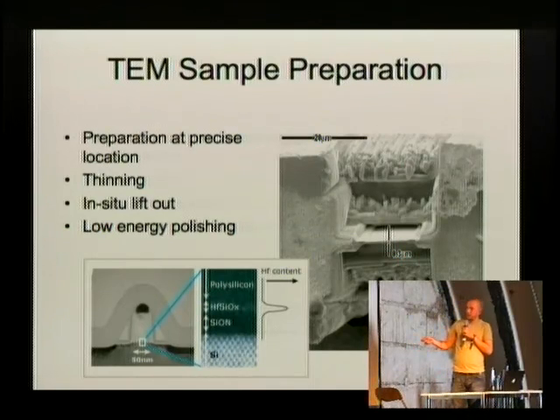Another thing we see here, I will talk about also on the next slide. In these microscopes, you can not only look at the image, you can also do, for example, some X-ray analysis, and that gives you very nice information about the material you're actually looking at. This is a structure that was made at our university. It has some very thin layers that were deposited in a chemical process. And the question was, how thick are the layers, can we see them, and what do they contain? So you prepare a lamella of the substrate in the same way I described. You put it into a transmission electron microscope or a scanning transmission electron microscope. One just looks through the whole substrate, the other one also has a scanning beam. The difference is not so big when it comes to resolution.